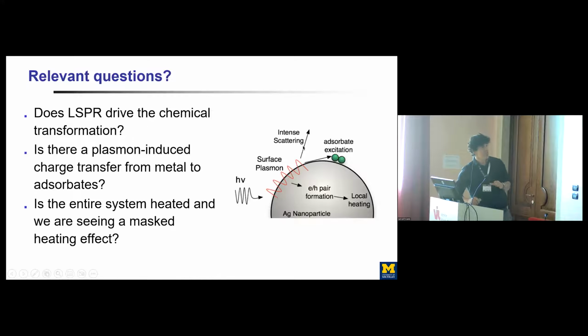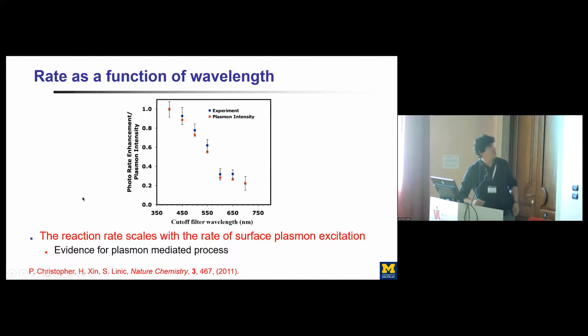So when you see these kinds of results, where you're shining light on a metal surface, and this is a low intensity light, and you see chemical reaction, there are a few questions that you would like to be able to answer. One is, does localized surface plasmon resonance drive this chemical transformation? Meaning, as a function of wavelength, does this happen exactly at the conditions in which these nanoparticles are collecting that light energy? But even more importantly, is there this plasmon-induced charge transfer that I've mentioned before, where you have excited charges scattering through this oxygen molecule, activating it in that process? Or is the entire system of silver nanoparticles and alumina being heated as a function of the interaction with light, and under the influence of this heating you're actually seeing a chemical transformation taking place? So we set out to try to answer some of these questions.